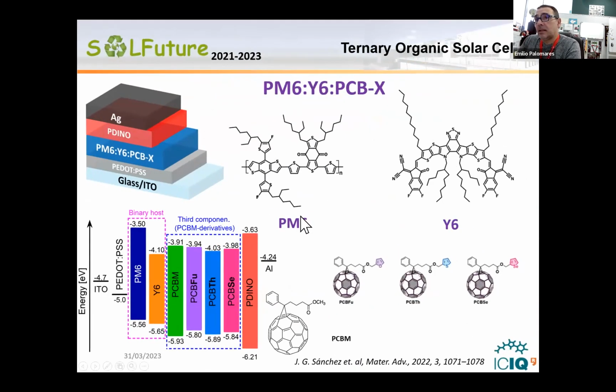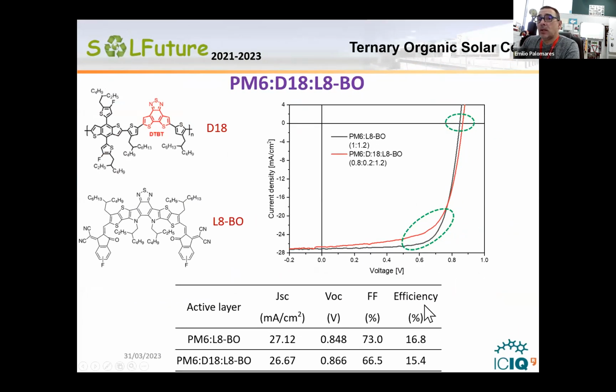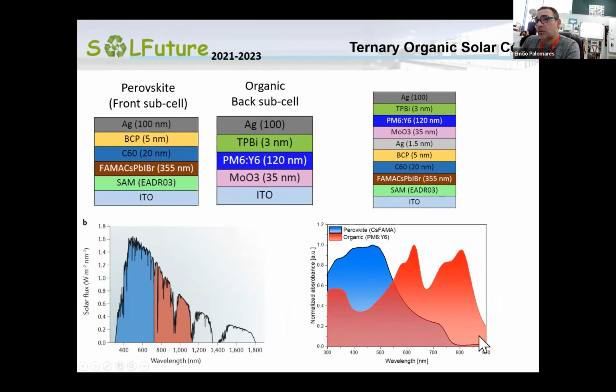So here are the materials that most people working on organic solar cells know. The non-fullerene acceptors, which people have now brought to about 16 or 18% efficiencies. We did some work with a colleague of ours in the Basque Country, at Polymat, to mix those non-fullerene acceptors with these fullerene acceptors in order to increase a little bit the current of the devices, because for tandem solar cells you want the current to be high. And that's what we get. We get devices with about 16% efficiency, 17% efficiency. The idea behind that, obviously, is to combine the perovskite and organic solar cell, so we have a panchromatic device with high current and high voltage.